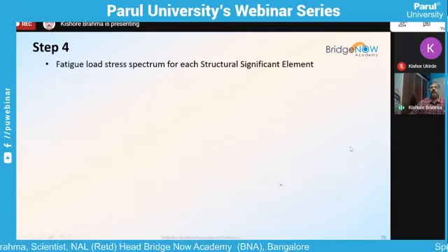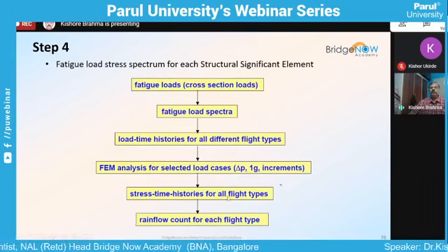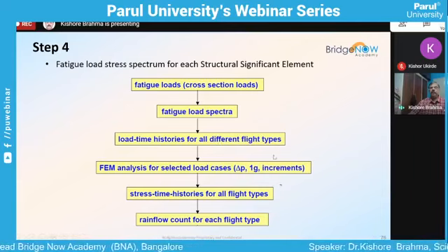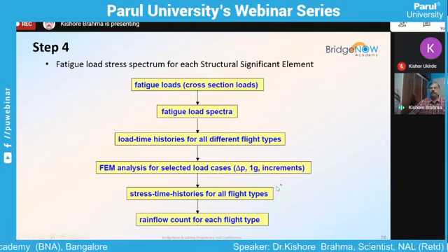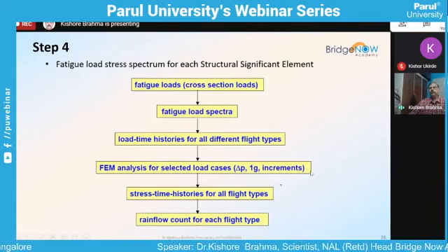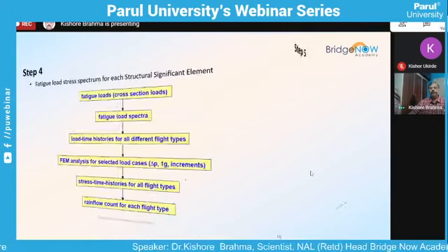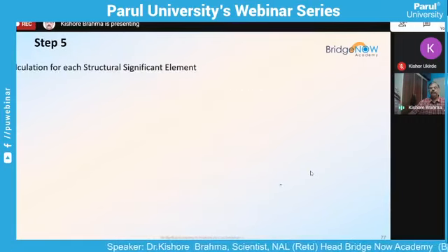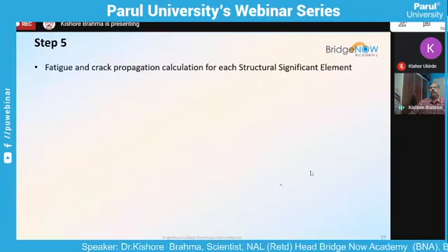Step 4 is the fatigue load spectrum for each structural significant element. There is a procedure available that I already described, not in much detail, but this is what you do: you get the load time history. Then use FEM analysis to convert the external load to the internal load. Then generate the spectrum from the exceedance curve. Then you do the rainflow counting technique to arrive at precisely what peak and trough constitute a cycle. Your step 5 is fatigue and crack propagation calculation for each structural significant element.